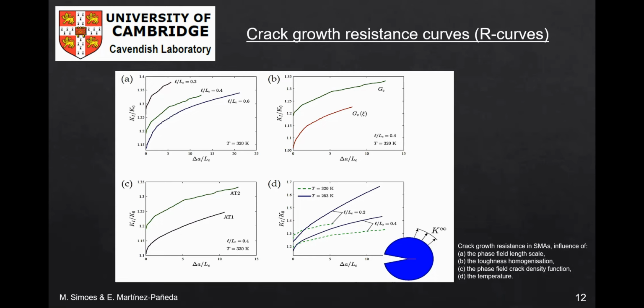In A, we see that when we lower the phase field length scale, which is equivalent to raising the material strength, we get a higher R curve. In B, we see a significant difference between assuming a homogeneous toughness or making the fracture energy dependent on martensite volume fraction by using the rule of mixtures. The martensite phase has a smaller toughness, so cracking initiates before.